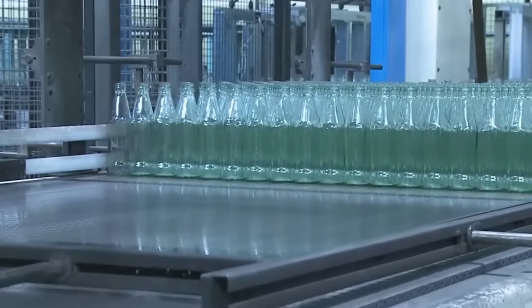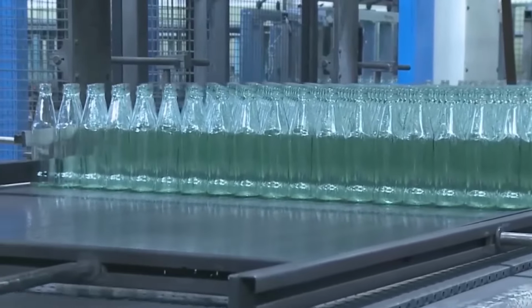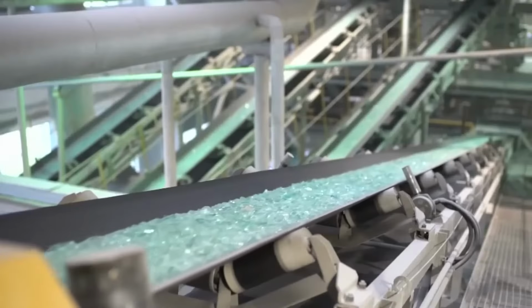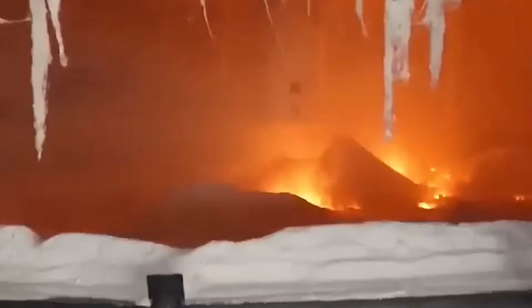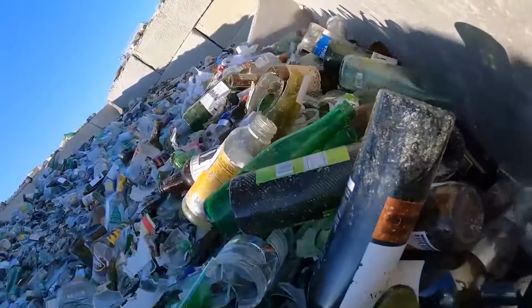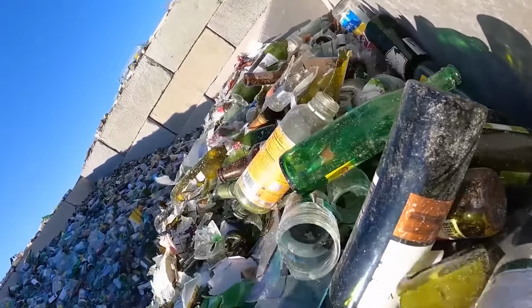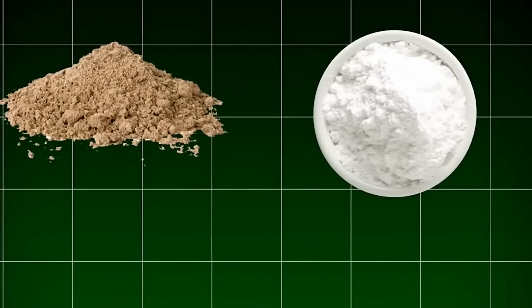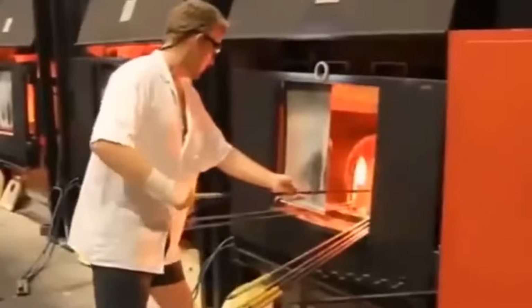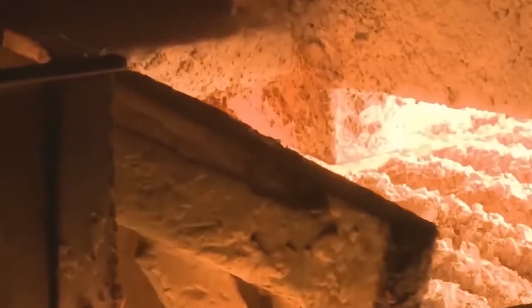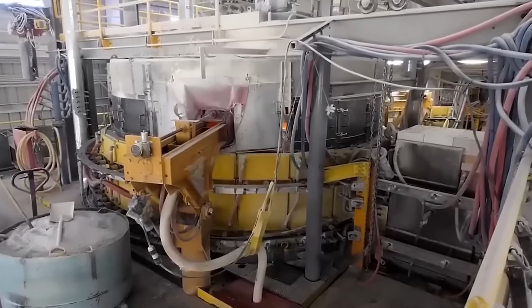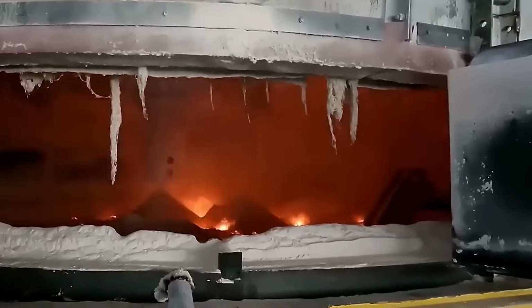One of the most significant benefits of recycling glass is its energy efficiency. Because cullet melts at a lower temperature than raw materials, it reduces energy consumption by up to 30%. Every ton of recycled glass saves more than a ton of natural resources, including sand, soda ash, and limestone. Many modern furnaces are powered by renewable energy sources like wind or solar, further minimizing the environmental impact. Massive electrodes inside the furnaces sustain the intense heat, while sophisticated systems regulate the temperature and prevent energy loss.